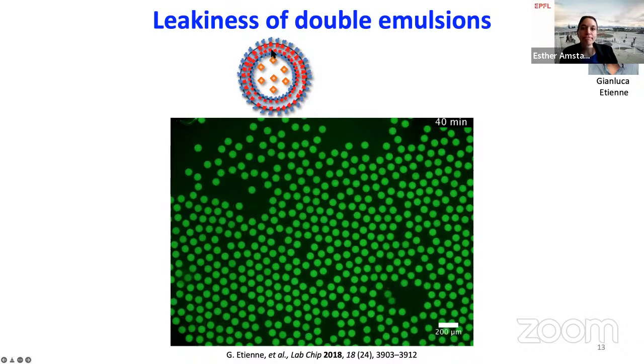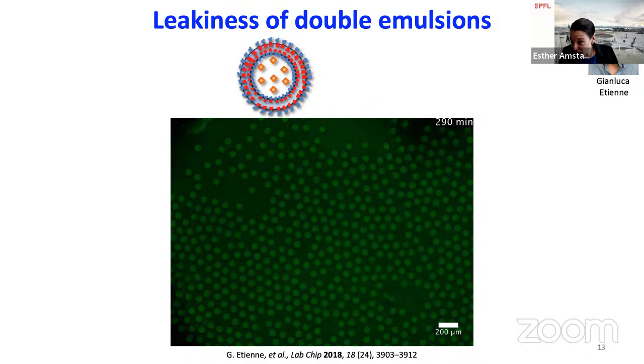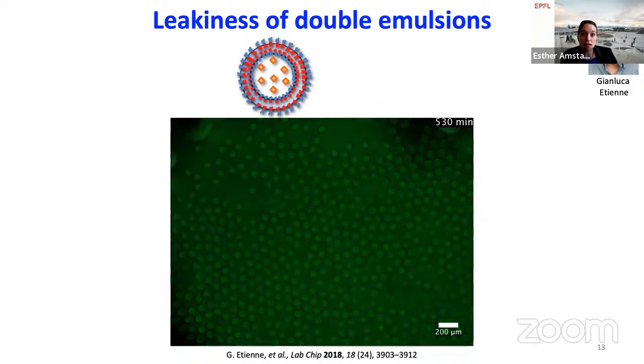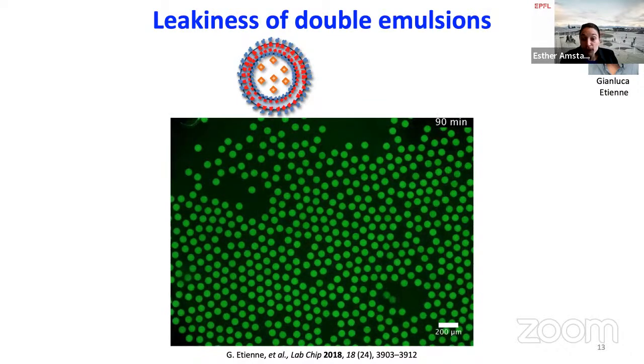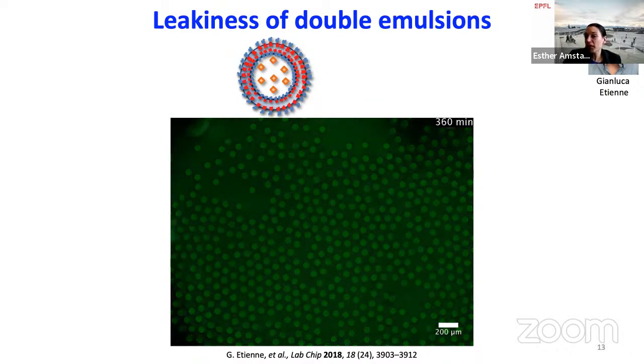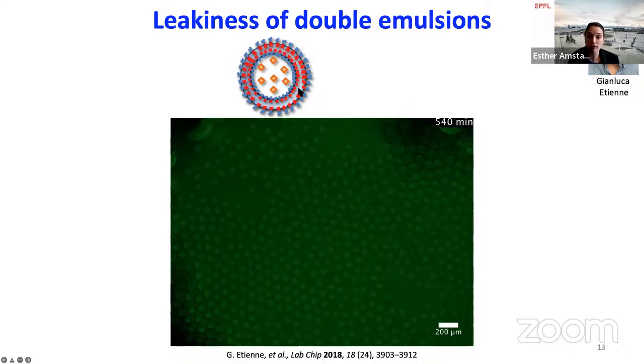And so I asked my first PhD student, in one of the first experiments that I did as an independent researcher, to actually incorporate some fluorescent labels within these double emulsions and see how long they remain inside. And I thought, because these fluorescent labels have almost no solubility in this oil phase, they'll stay there forever. But what you actually observe is that, depending on the exact composition and concentration of the fluorophores, they leaked out within a couple of minutes to a few hours.